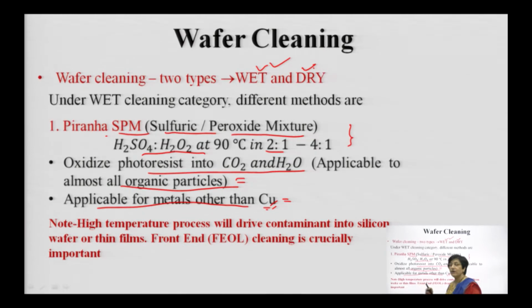Now, one thing to remember here, a note of caution is always to be considered. Now, what is that note of caution? As the piranhas attack ferociously, this particular solution also attacks the wafer substrate very strongly, and therefore, if the temperature is elevated too much, it will drive the contaminants into the silicon wafer or into thin films.